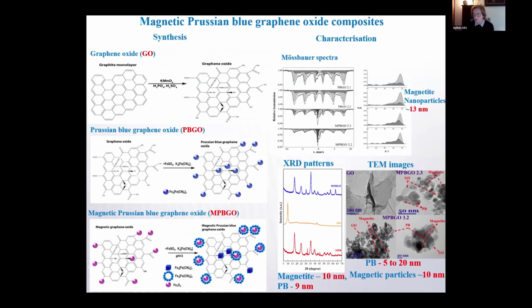Prussian blue particles of non-cubic shape were observed in sample 2.3, while in sample 3.2 very well shaped cubic particles were defined, and the particle size was estimated between 5 and 20 nanometers. Magnetic particles also were found in this composite. Their size was about 9-10 nanometers.